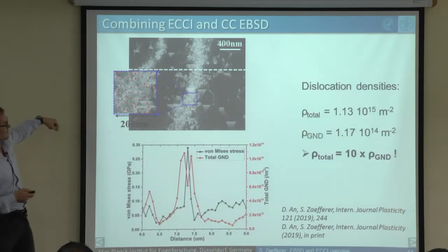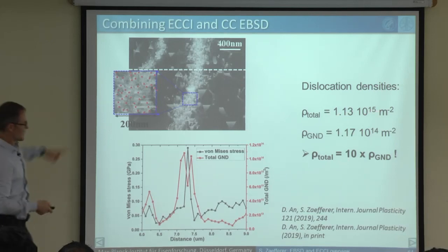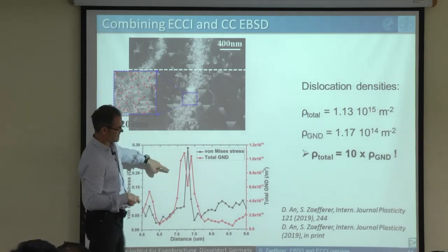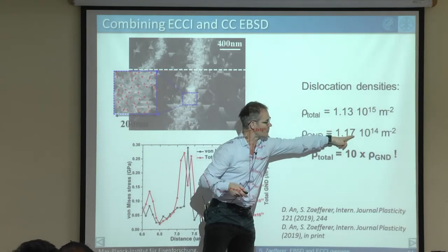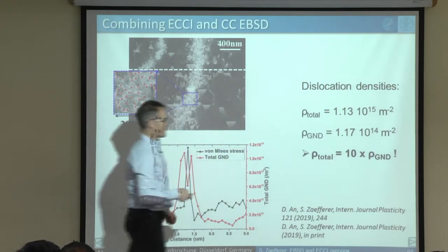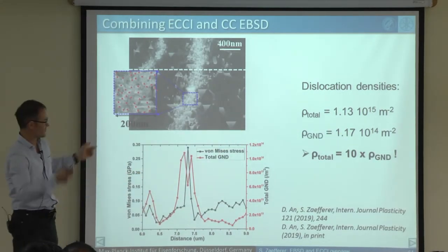How high is it? I don't remember. The total dislocation density is just 10 to the 15, and the GND density which we calculate is an order of magnitude smaller, 10 to the 14, and that means 10 times difference, yeah?